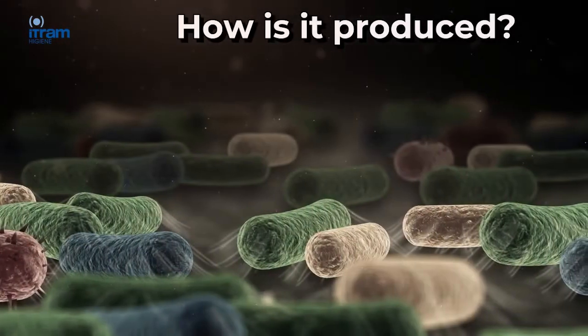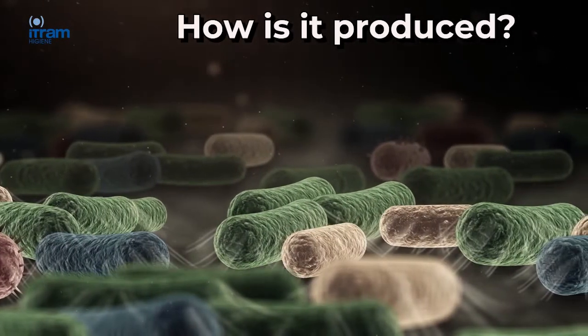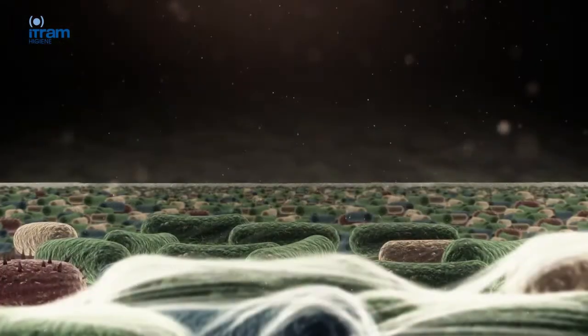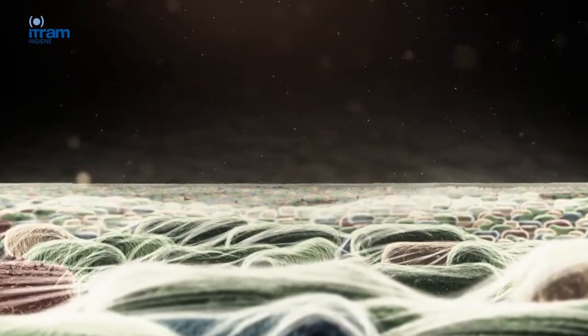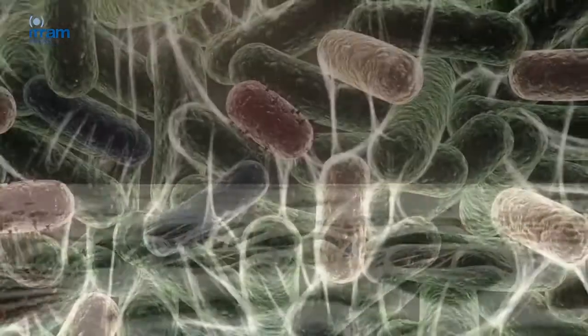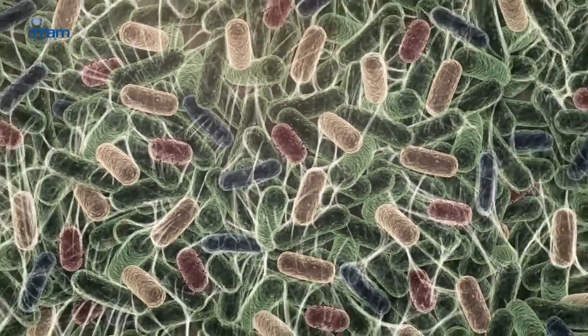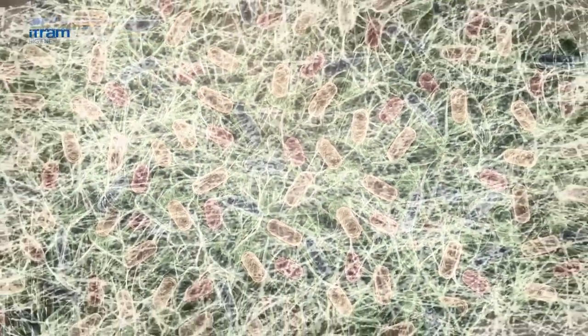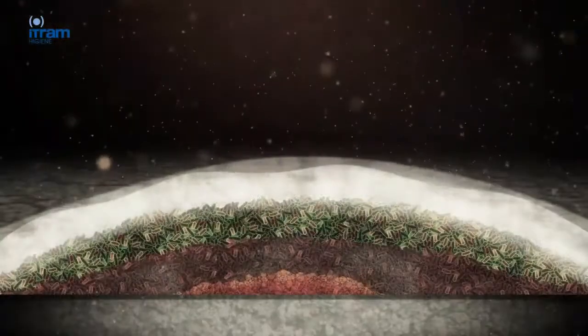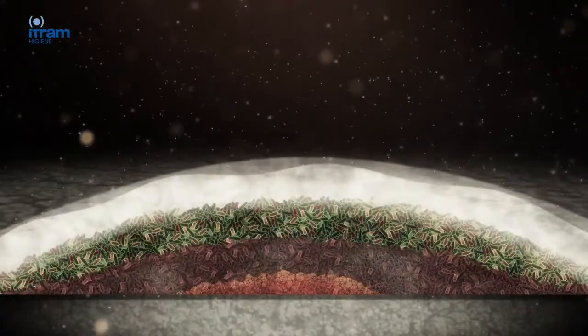How is it produced? Its principal cause is the adhesion of microorganisms on the implant surface and the formation of biofilm. It takes place due to a complex interplay of several factors such as bacterial load, microorganism-specific factors, host factors, surgical technique and perioperative environment. In order to understand the microorganism's implant surface relationship, it is important to know the different stages of biofilm formation.